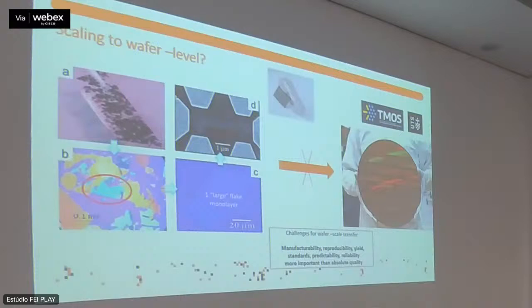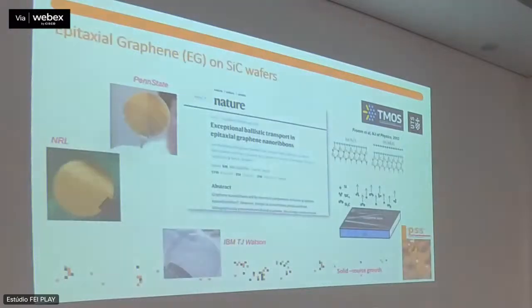The problem is that once you have your graphene layer covering your wafer, all of the subsequent processes that you would have to go through, like thermal loading, mechanical stress, and perhaps even chemical mechanical polish, would probably make your structure at some stage just peel off. Because remember, the material in principle doesn't have any bonding to the other layers in the Z direction. So what we want to do is have a different take.